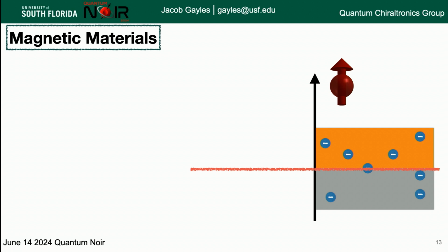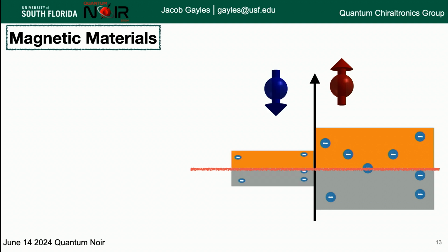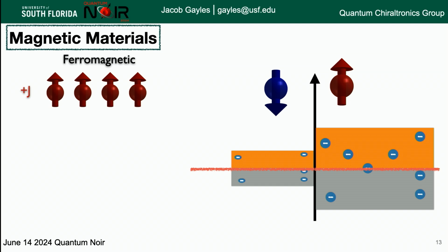If we take a single magnetic atom and look at the local density of states just for that atom, we can split up the density of states into two, right? So we can split up the density of states for the spin up and the spin down. This is the metallic case here. And that produces a local magnetic moment. And when that is on all the atoms, then you can have some ordered magnetism throughout.